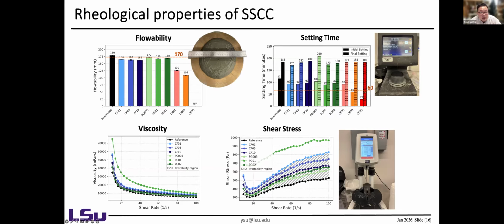And for the setting time, because that is relevant to the opening time and also the printing, the stiffness development of the 3D printing. So we found out that the carbon fiber and the pristine graphene all behave great, which has a longer setting time compared with the carbon black. So for some mix we design with 5% or 3% of carbon black, its setting time is actually pretty quick. And we further want to identify what is the printing zone or printability region.